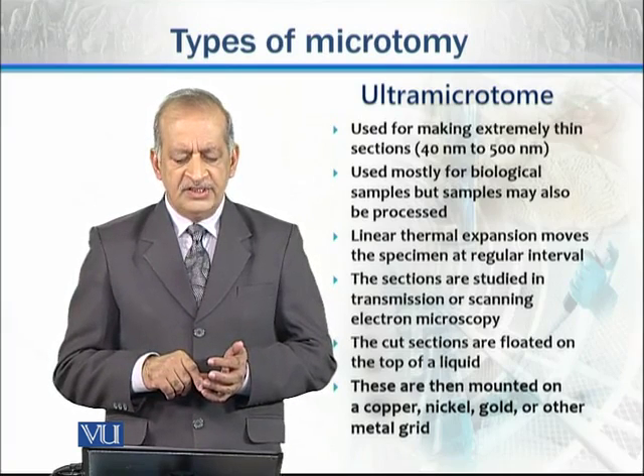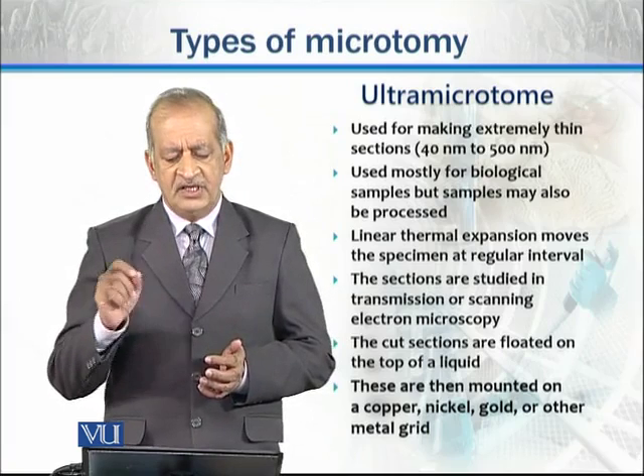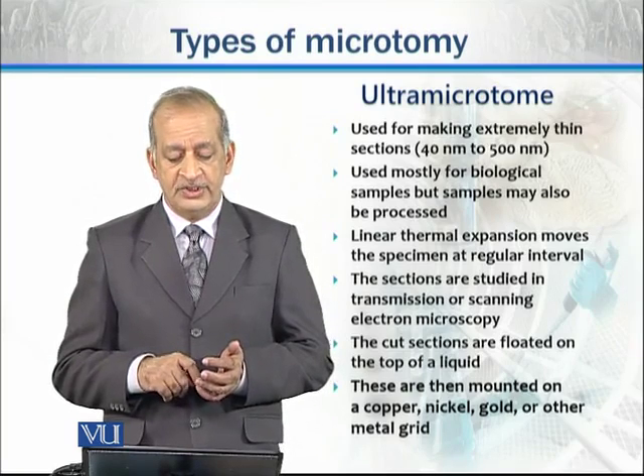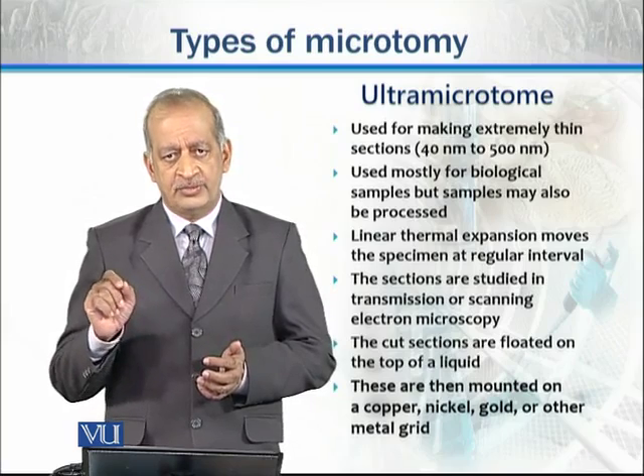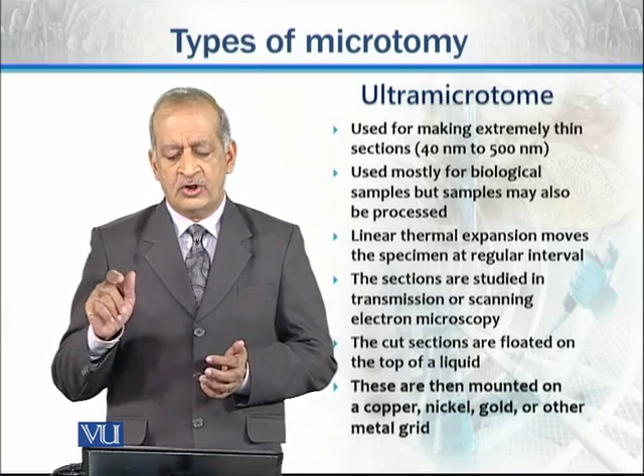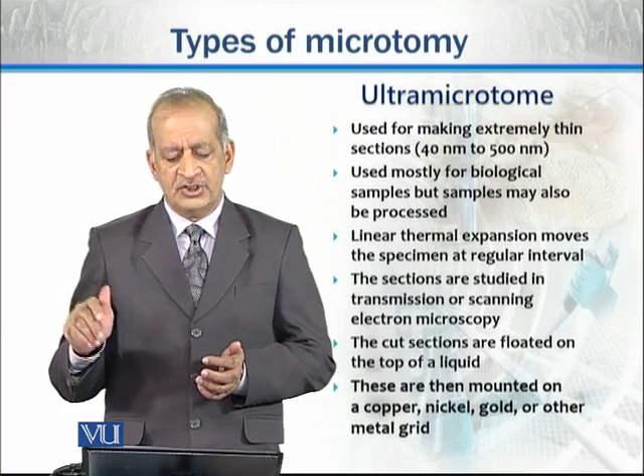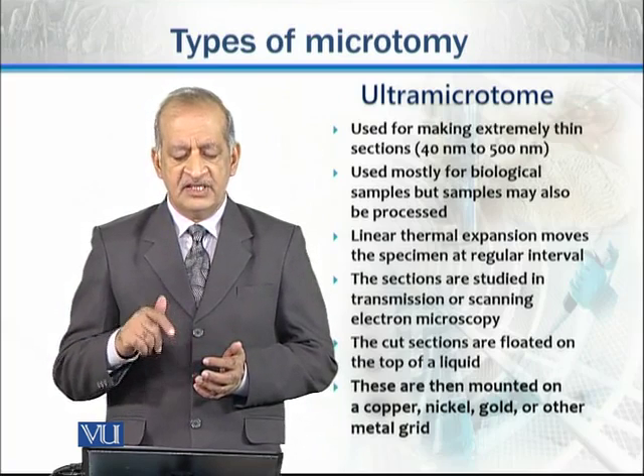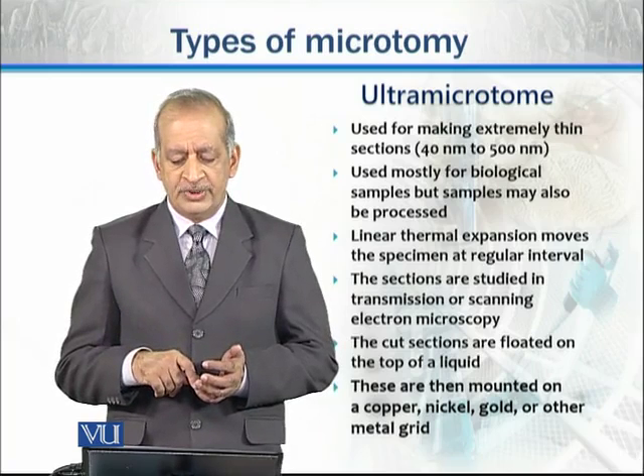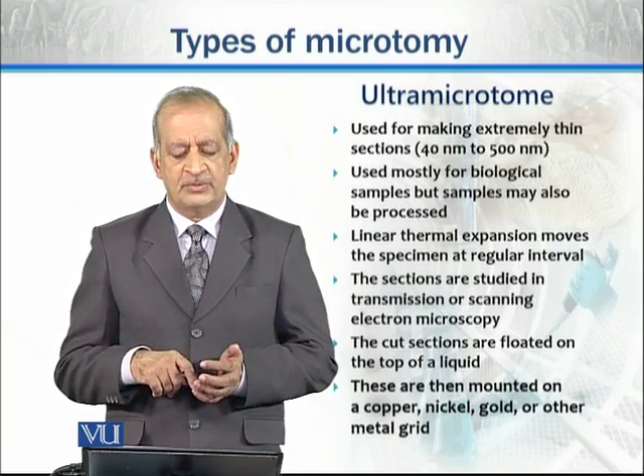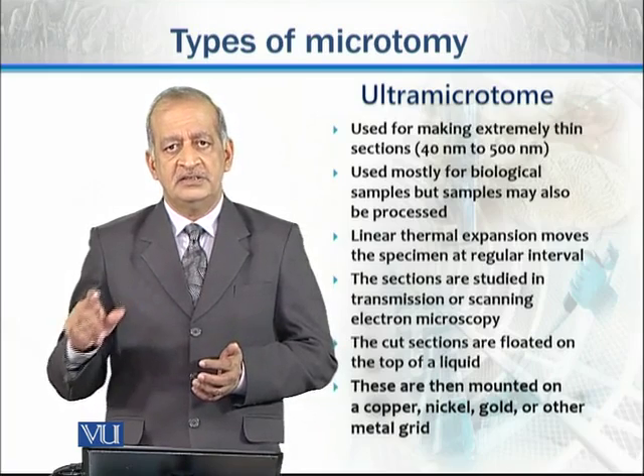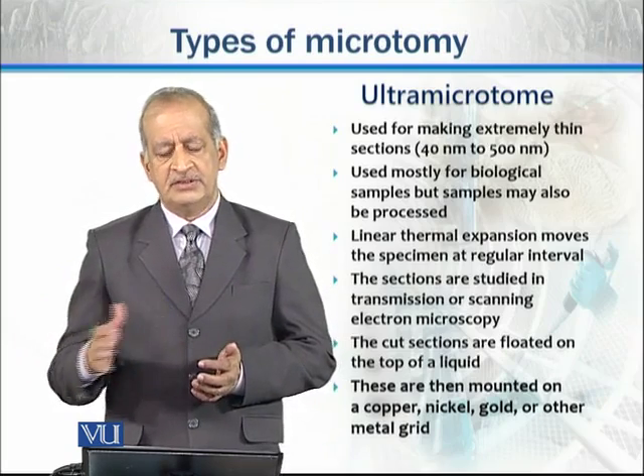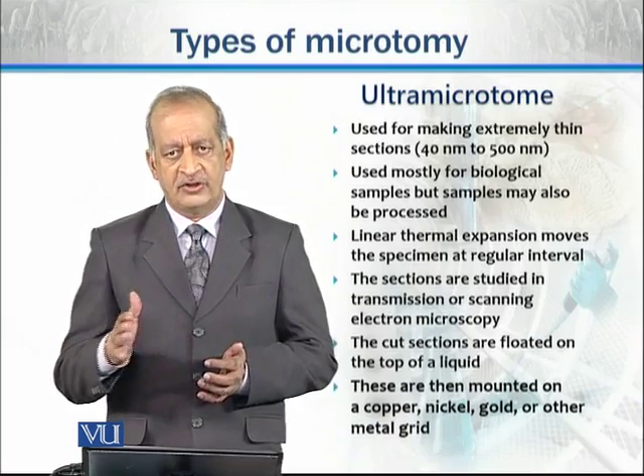The sections obtained are studied using transmission electron microscopy or scanning electron microscopy. The cut sections are produced in a floating condition on the surface of a liquid, and these floating sections are then mounted on a support grid made of copper, nickel, gold, or other materials for detailed structural examination under the ultramicroscope or other microscopes.